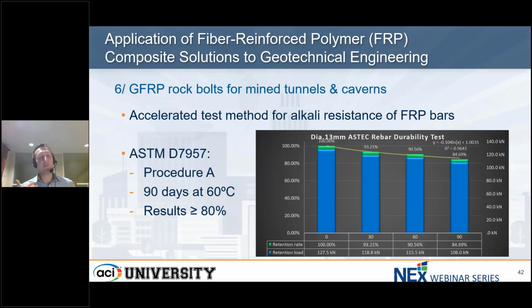So here, for example, there are so many different tests performed with large variation in the duration. Also, whether you use moist concrete or a water solution, an alkali solution. Also, whether you apply stress at the same time or not. But in general, again, best is to refer to ACI for the guidance. The requirement in ASTM D7957 is to be over 80% after 90 days. And so this is again showing that the behavior of the material is highly predictable.